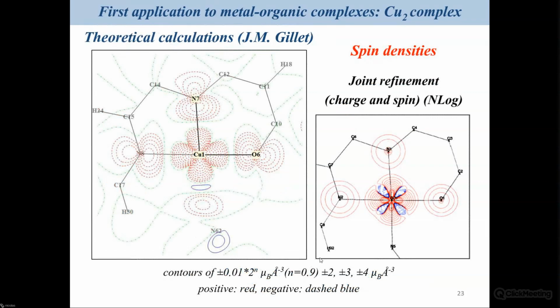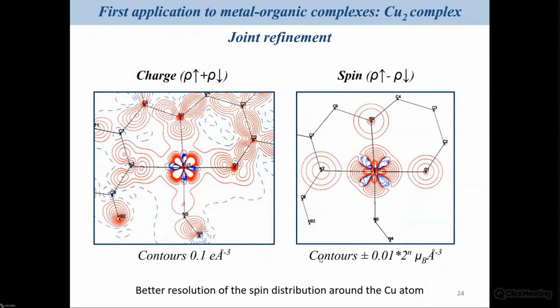So we already asked people to do theoretical calculations to compare what we obtain from our experimental approach to that theoretical calculation. And this is what has been done by Jean-Michel Gillet. And you see, comparing both models, that they are already very close, because the spin density predicted by Jean-Michel using DFT calculation is very similar to the one we obtained using the joint refinement. So at the end, we have a very good resolution of the spin density distribution around the copper atoms.